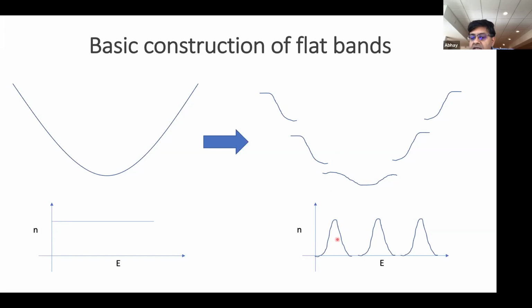And each of these subbands is going to have a peak in the density of states that corresponds to one or more Van Hove singularities in the band structure. And so at its most basic level, this is all that there is to it. You apply a periodic potential to a two-dimensional band, and this periodic potential is going to create for me peaks in the density of states. And once again, because you can tune the doping at will, you can enter one of these peaks in the density of states and ask what happens when you enter into those peaks.